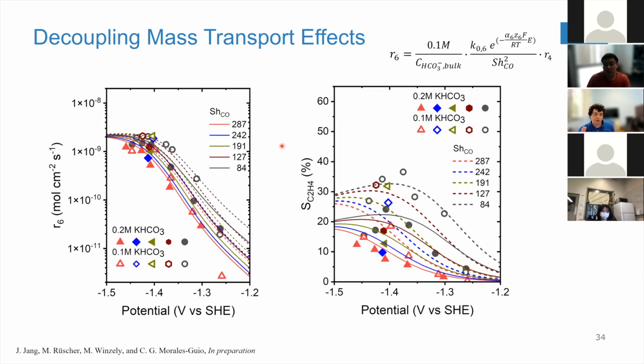And with that, I will just finish by pointing out that you can also describe selectivity. So now that you have all these different rates, and how they are affected by mass transport or by different conditions, you can actually identify what the optimal conditions are to, for example, have the highest selectivity for ethylene. This is for a flat copper. What we identified is that the longer the residence time, so the smaller the Sherwood number, and the lower the bicarbonate concentration, the more selective your system will be for the production of ethylene. But again, this is all the same catalyst. Just by changing the rotation, the mass transport properties, you actually can tune the selectivity for polycrystalline copper.